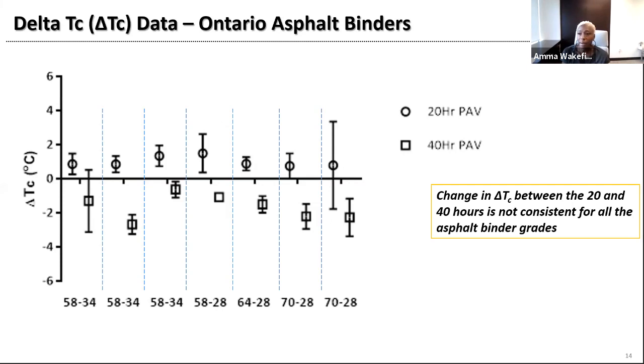Comparing values, in Ontario, we conducted an interlaboratory study of 5 labs to test various parameters for asphalt binders that are used in Southern Ontario. And delta TC was one of the parameters that we calculated from the tests that were done. And here you're looking at delta TC values for 20-hour PAV aging and 40-hour PAV. So 20 hours PAV is the standard in the current testing for PG grading, but 40 hours is being discussed because we want to look at extended aging, and also there are discussions about whether or not the 20-hour aging is severe enough. So we compared 20-hour and 40-hour PAV aging and calculated the delta TC values.